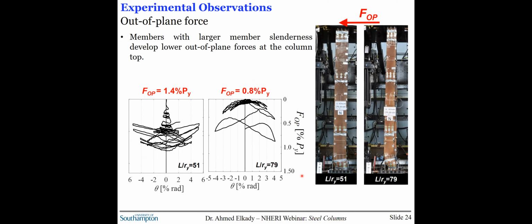It's worth showing here that this unique setup actually enabled us to evaluate and quantify the out-of-plane force at the column top, where you typically would have bracing. So essentially what we observe is that members that have larger member slenderness or global slenderness, L over Ry, will develop lower out-of-plane forces. And the thing here is that the stockier columns tend to buckle later and develop larger amounts of cyclic hardening. And eventually this tends to exert large out-of-plane forces at the top compared to the more slender columns. So again, these are all unique data that have not been measured in prior testing programs. And this also can be used to evaluate the bracing design provisions in the steel specifications, for instance.